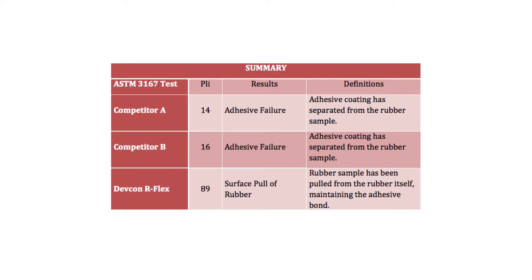Summary of results. Competitor A and Competitor B both had adhesive failures, where the coating separated from the rubber sample. DevCon RFlex had surface pull of rubber, showing the rubber pulling away from itself.